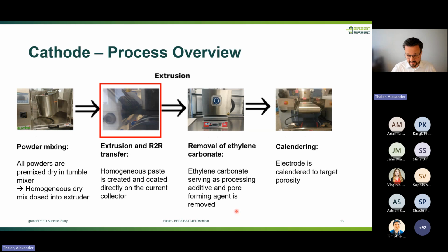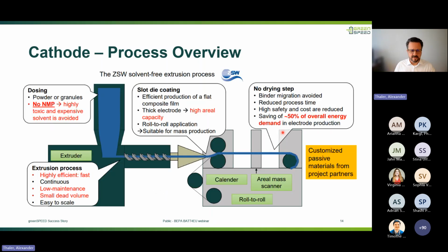Dry processing, a very brief overview on the left. The dry powder is mixed, hopefully homogeneously mixed. Then it's transferred to the extrusion and roll-to-roll transfer. We have ethylene carbonate as a processing additive that needs to be removed after the extrusion process, and then calendering is done.